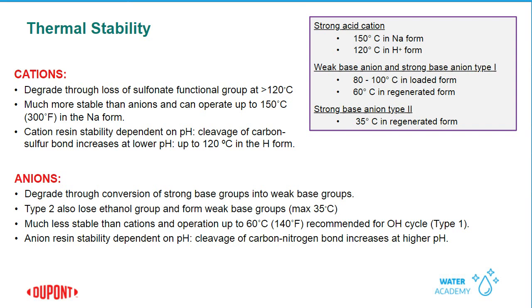Now, that is important to know, because you can imagine if you have a vessel and you fill it up with a cation resin, a strong acid cation resin in the sodium form, and you would expose that to an acid, you will convert it from the sodium to the hydrogen form and increase the hydration, and because of that, the resin will start to swell. Now, the resin will not collapse. The resin is extremely strong, but what will collapse or deform is your vessel. So you can imagine a good understanding of how resins act when they change chemical form is critical if you operate a system or if you're handling a resin.